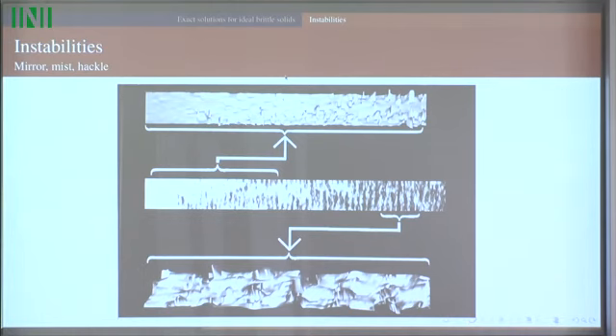And we had found an instability in dynamic fracture, which manifested itself by when the crack was moving relatively slowly, 20-30% of the Rayleigh wave speed, the crack surfaces were smooth, and then they became rougher and rougher, and then the surface became very jagged. We published several papers on it calling it an instability, and the reason we called it that was that it was a perfectly good English word that covered the fact we had no idea what it was.